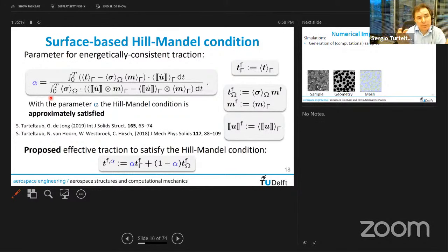It does require us to embed cohesive elements everywhere, and it automatically creates a numerical issue, which is the artificial compliance coming from the compliance of the cohesive elements. Luckily, we did find a way to extract that information. I showed that on some of the slides. I didn't talk about it, but there is a term in there connected to the compliance from the cohesive elements. All in all, not the best technique, but at the same time, not the worst one. Computationally, simulations could vary from 1 hour to a couple of hours to a full day.